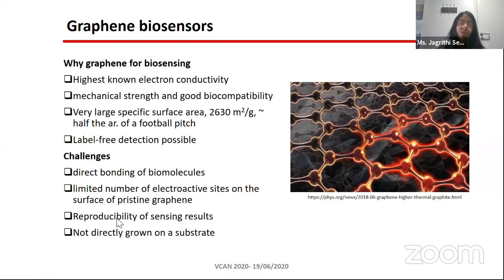But when I did the literature survey of the biosensors for Alzheimer's disease biomarkers, there are not many graphene biosensors. The reasons may be that the reproducibility of the results is not as good, and there are also issues with the specificity of these biosensors. On the graphene surface, the biomolecules cannot be attached directly because pristine graphene does not have any electroactive sites to attach them, and it cannot be directly grown on the substrate. These are the challenges usually present in graphene biosensors, and that may be the reason why there are not many graphene-based biosensors, especially for the detection of beta amyloid, which is what I've been focusing on.